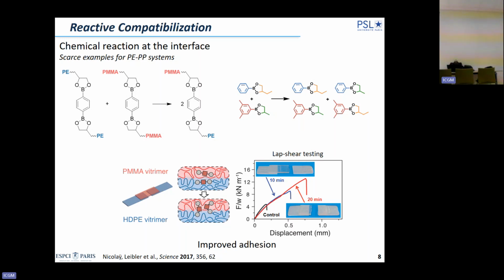And what is very nice is that the boron-oxygen bond and the boron-aryl bond are both very strong. They are thermally resistant, they are not sensitive to oxidation, and this exchange can take place without the need for a catalyst. So it's pretty interesting if you want to go to reactive processing.